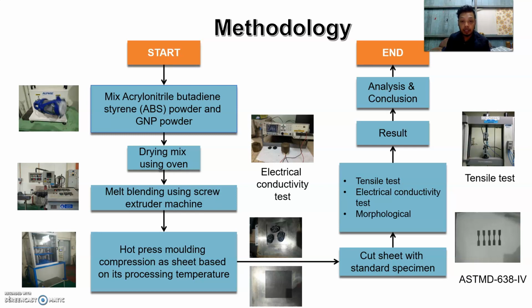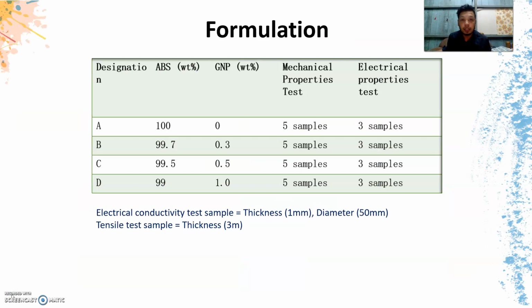Then I test the sample using a tensile test to get mechanical properties such as tensile strength, Young's modulus, and elongation percent. For electrical properties, I use an LCR meter to test electrical conductivity. And for morphology, I use scanning electron microscopy, SEM, for testing. After that, I will get the result and I will explain the result in the next slide. Okay, this is the formulation of the experiment of GNP based ABS composite.